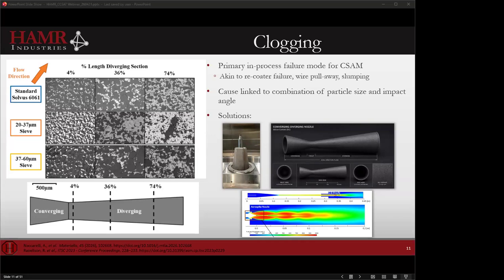And the last way that the community's been looking at solving this, and maybe the most novel way, is changing our nozzle design. If you're familiar with rockets and space, aerospike nozzles are a novel approach that a lot of people have been trying to get to work. We can take that into cold spray, and what it allows us to do is inject our powder past the throat of the nozzle and into a region where the fluid is a little bit cooler, and also more importantly, into a region where it's not likely to impact anything, because it's past the diverging section or past any wall that it can impact. So there are solutions. It's an ongoing problem, something that's monitored, and something that needs to be designed around.